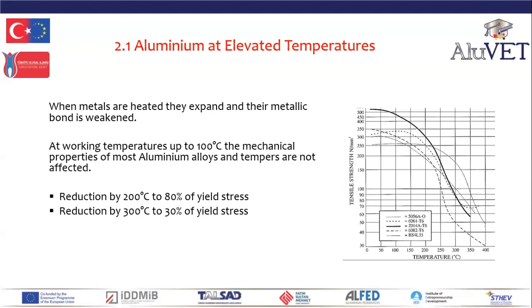Now, this is such an important property because it enables aluminium to be hot formed, hot rolled, particularly extruded and forged using low forces at relatively low hot working temperatures. You would hot work aluminium at 300, 400 degrees C. You hot work steel at 1200 degrees C. Very, very important property of aluminium. The fact that it loses strength at relatively low elevated temperatures.